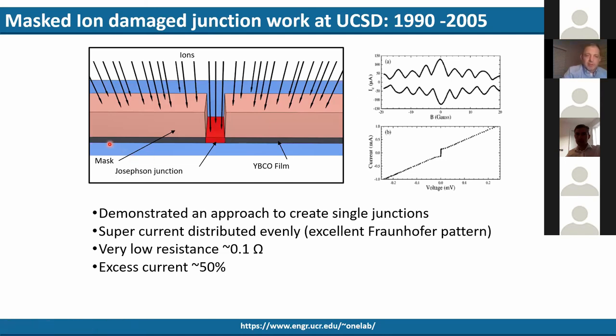Here's a slide that really shows how they did it. So here is a YBCO film. And then here's a high aspect ratio mask that they built over top of it. And then they just used RIE etching and E-beam lithography to make this channel in here. And when you irradiate this down, ions get stopped in the mask here, but they get through, and they can reduce the TC here. And in those old days, when they tried to make that weak link insulating, transport didn't get through. Nothing got through because the smallest dimensions you could really practically make using this fabrication process are greater than 10 nanometers. And once you get greater than 10 nanometers, you can't get tunneling through the barrier or an insulating barrier.